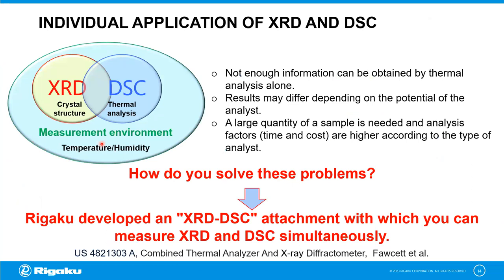Now, we can apply both XRD and DSC individually, but it actually turns out it's very useful to do this simultaneous experiment. One reason is that we can remove the correlation problem of running the sample in a DSC and then running the sample in an XRD tool. I have to point out that we developed this attachment about a decade and a half ago, but the original concept came from Tim Fawcett and his group at Dow Chemical in the late 80s. In fact, this patent was first published in 1989.